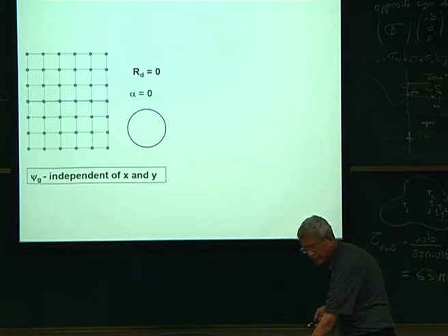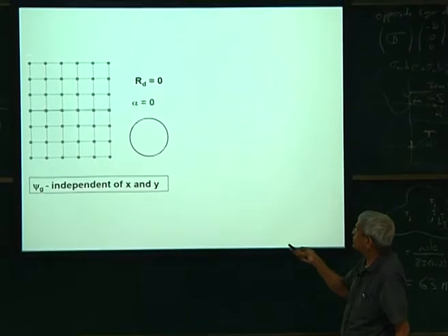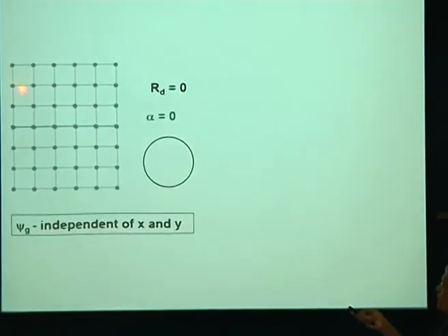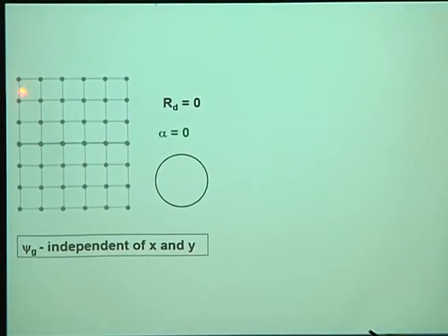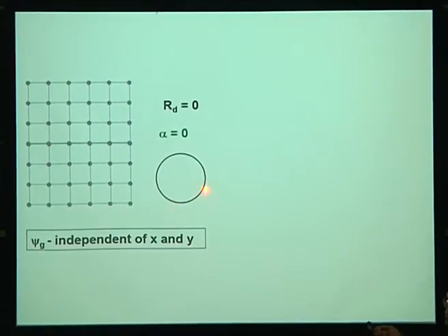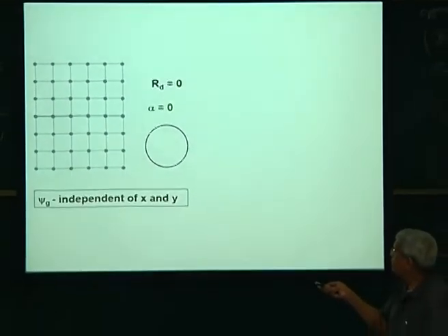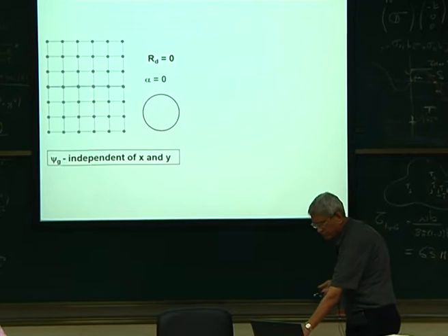I will not go into detail, but essentially, if you assume alpha equals 0, then as the beam passes through this sample, there is going to be some scattering. The amplitude gets reduced, and this is what the phasor diagram represents. It comes back to 0 at the end of it. So we find that the defect is not being seen.